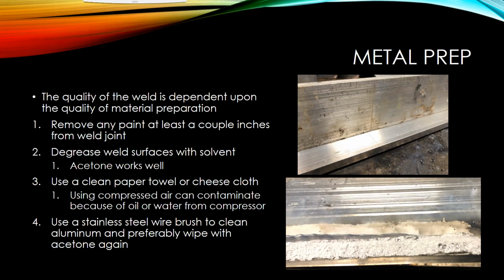One thing that I've seen guys do in the past is they'll grab an air compressor and just blow off the material and wipe it down. But one of your issues there is you could have just introduced oil or water from the compressor onto that weld surface. And now you're going to go weld it and it's going to draw that into the weld joint itself. And you could have more issues like porosity or a weld fail.